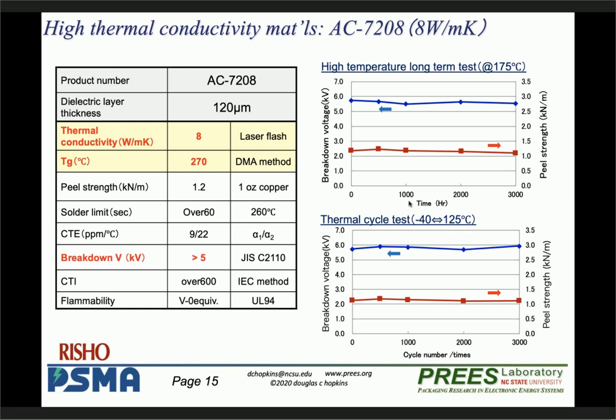But the point here is, if you look at the graphs that we're showing, the breakdown voltage, the left side with the blue line shows 120 micron thick sheet across 3,000 hours. They use partial discharge tests when they do these. You can see it's very stable with the voltage capabilities, 5 kV at 120 microns, something like 44 kV per millimeter. We're up in that range. I think that's what it is.